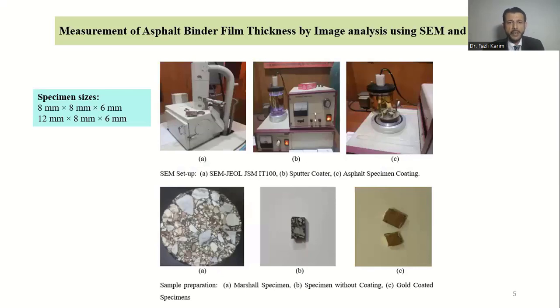Therefore, a SEM-JEOL JSM IT100 scanning electron microscope with a sputter gold coater was used at magnifying power ranging from 250 to 30,000 and bar scale of 100 to 0.5 micrometer. The Marshall specimens were basically sliced in order to visualize the internal micro details of the asphalt mixture, and the required specimen size was obtained. Then a point of interest was designated on this specimen, and a coat of gold was also applied on the specimen so that the micro details can become visible during morphological analysis using micro level equipment.